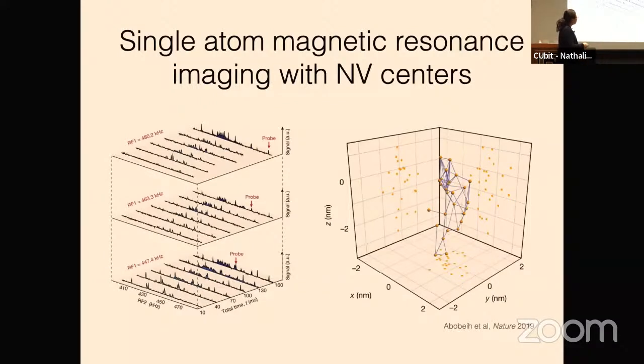So just to show you the promise of this probe, there's this beautiful work from Tim Taminiau's group from a few years ago, where they were able to push this almost to its logical limit. They have an NV center that's deep in the bulk of diamond, and they do some pretty complicated NMR pulses to look at different carbon-13 nuclei in the vicinity of the NV center. And they use this to do magnetic resonance imaging of each of the positions of these carbon-13 nuclei. So they're able to look at the positions all the way down to this kind of sub-angstrom resolution of, I don't remember exactly how many it is. I think it's in the title of their Nature paper. It's like 27 carbon-13 nuclei or something. So I think it's pretty clear that if you could do something like this, but for random targets, not things that are just deeply embedded in the diamond, this would be a very powerful tool that would really change what we're able to do in terms of nanoscale sensing.